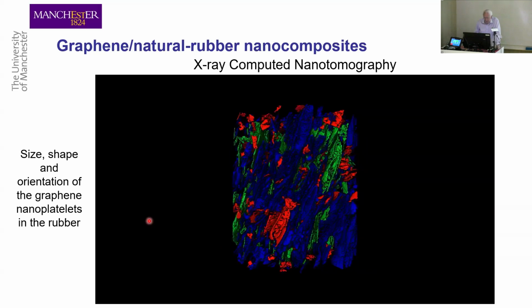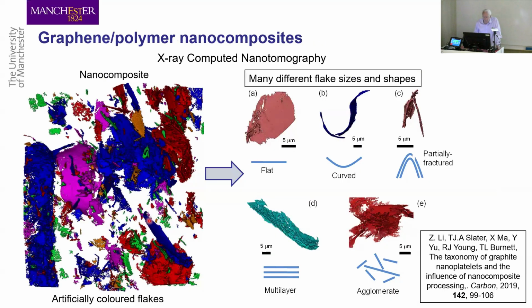And it turns out, of course, that in a nanocomposite, the graphene is nowhere near as beautiful as you might expect. If you look at the individual flakes, this is again artificially colored flakes, you can see you get a whole family of different sorts of flakes in the material. You can get some flat flakes, you can get curved flakes, you can get partially fractured ones, you can get multi-layer ones, you get agglomerates. The whole thing can be something of a mess when you try and make a nanocomposite, if you just fragment some graphite and try and make a composite in this way. So you have to be very careful to know what you're looking at. You get big flakes, small flakes, whole range of different things.